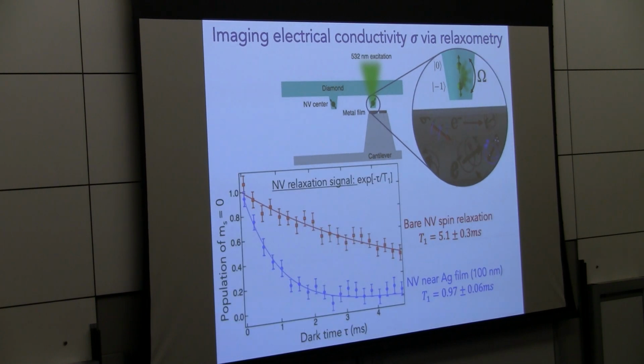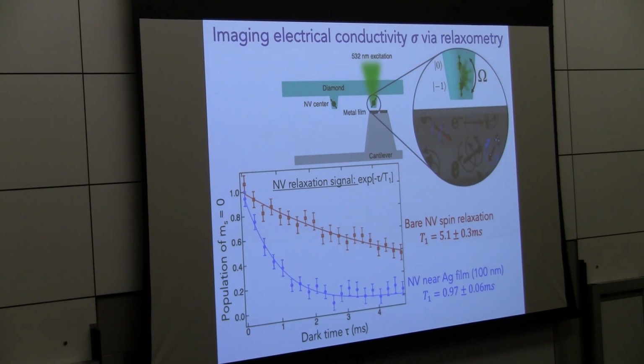And so in the experiment, what we did is we measured the T1. This is, in this case, our sensing signal. When our NV is really far away from the conductor, we measure a T1, and that's the characteristic decay. In this measurement, I can polarize the NV center to the 0 state, which is a very non-equilibrium state, and wait for some amount of time to see how long it takes to equilibrate to some thermal population between the 0 and 1, where it gets darker over time, because that one state is darker. The characteristic time scale of this decay is indeed the T1. Okay, so this is how we do the measurement.